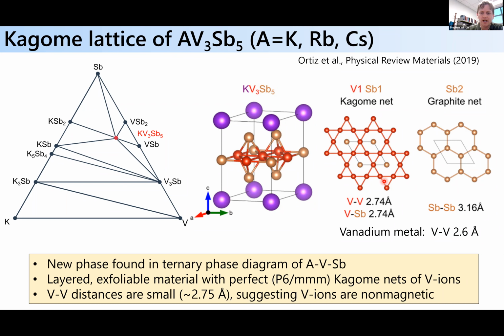Okay, and one thing to note is that the kagome lattice in the system is an ideal kagome lattice and remains so down to the charge density wave ordering temperature in the system, which I'll motivate in a moment. The other thing to notice is that the vanadium distances are reasonably small, 2.74 angstroms. That's comparable to the vanadium distances that you would find in vanadium metal, for instance, right? So this is already hinting that in this system you would have substantial covalency or delocalization effects, and the vanadium ions might be non-magnetic.